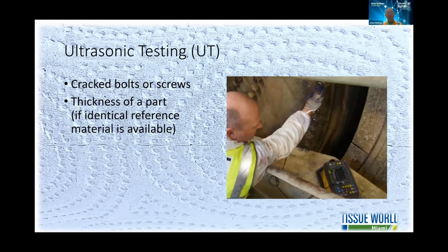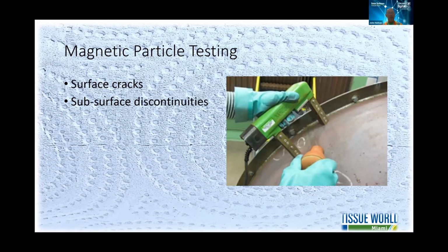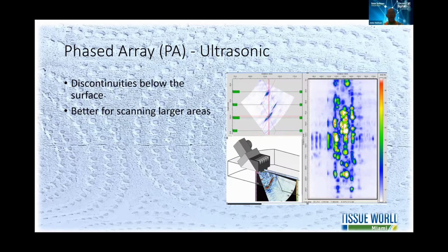Ultrasonic testing, something very common, normally every 5 years, for cracked bolts or screws, thickness of the part, if the identical reference material is available. Magnetic particle testing, where you would look for surface cracks or subsurface discontinuities. For steel Yankee dryers, a common approach would be phased array ultrasonic, which can look for discontinuities below the surface. This technique is better for scanning larger areas. If you had to scan a whole Yankee dryer, for instance, this would be the tool used.